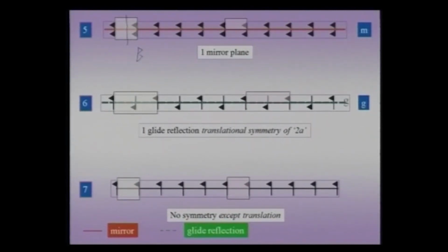In other words, the crystal I have generated here has a lower symmetry than the original lattice, and the only surviving symmetry is the horizontal mirror, which is MH. The translation symmetry remains, so I can write the symmetry of the crystal I have generated, number 5 crystal, as T MH. So this crystal, as you can see, has a lower symmetry than the lattice I used to generate it.